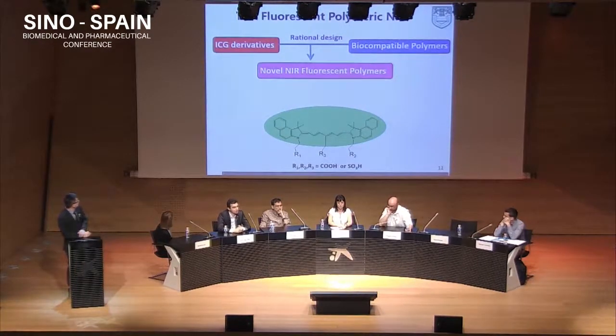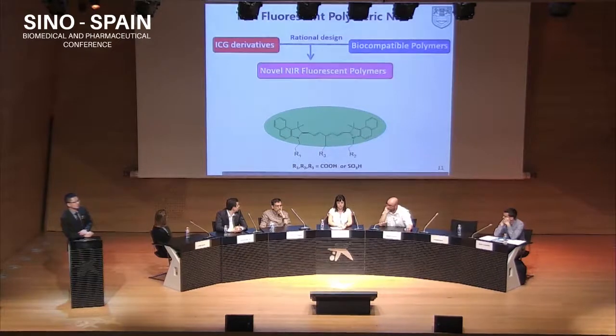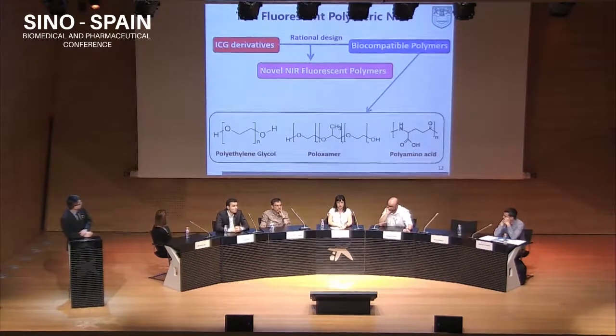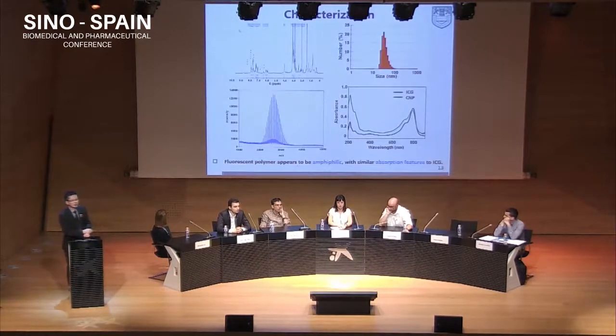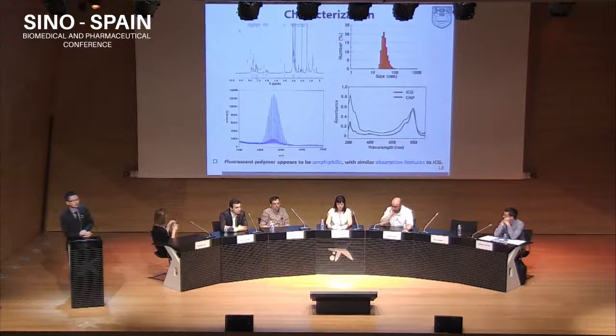For ICG derivatives, I modified the side chain number, length, and the functional group of ICG. And then for biocompatible polymers, I use the FDA-approved polymers such as polyethylene glycol, poloxamer, and polyamino acid, and so on. Here, I only report one of our polymers, we call it ICG-PEG, composed of ICG derivatives and polyethylene glycol. Its molecular weight is about 2000.